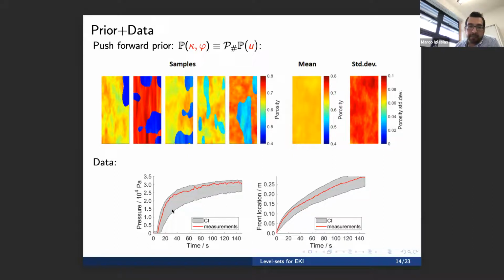Then we have these synthetic measurements. I'm showing here pressure from 1 out of the 6 locations, and front location from 1 out of the 7 sensors. Again, synthetic measurements generated with the same simulator that we're using for the inversion. For each of these samples, we run the simulator, and we produce some confidence intervals for the prior, which you can see here. So it's not that bad.